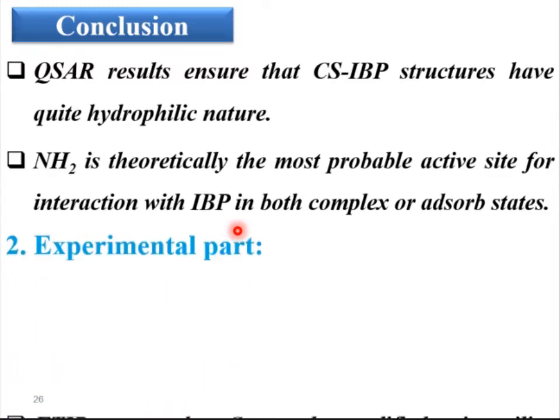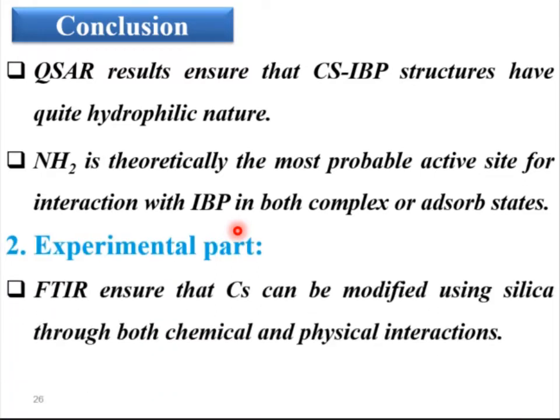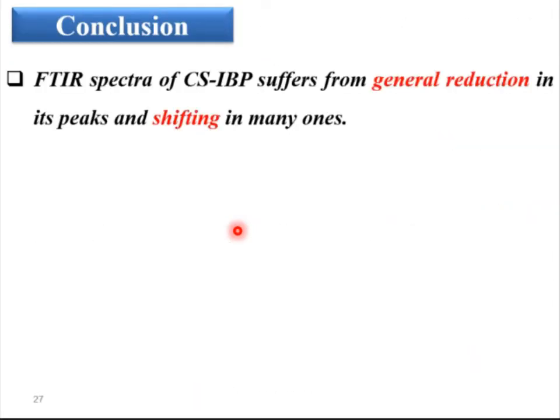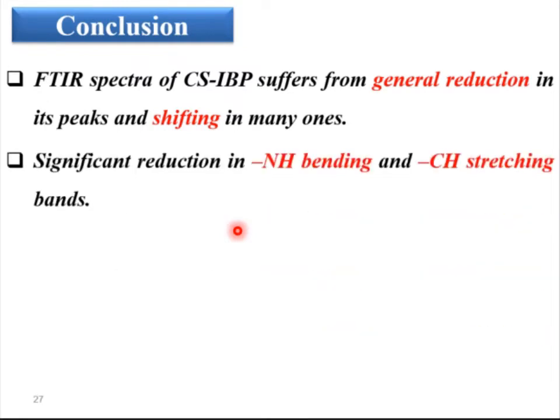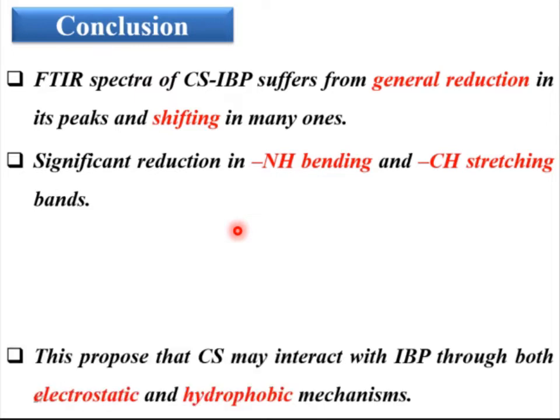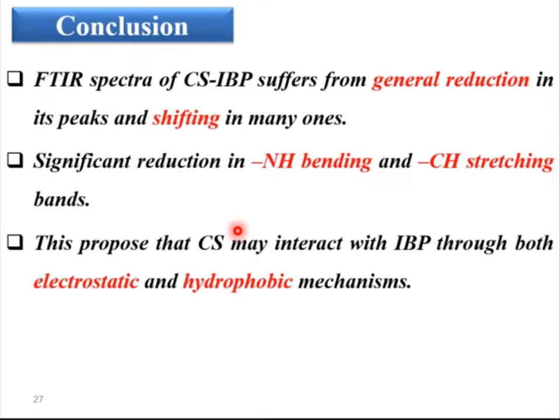Then, in the experimental part, it was ensured that chitosan can be modified using silica through both chemical and physical interactions. The IR spectra of chitosan silica ibuprofen show a general reduction in all peaks and shifting in many of them, with significant reduction in NH2, NH bending, and CH stretching bands, referring to two main mechanisms for interaction of chitosan with ibuprofen: electrostatic and hydrophobic mechanisms.